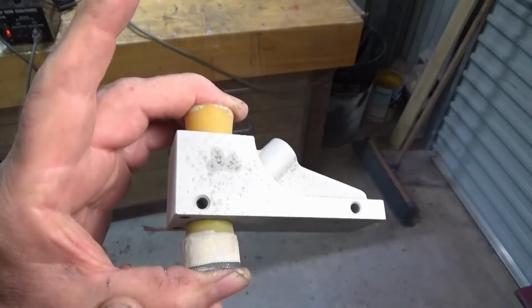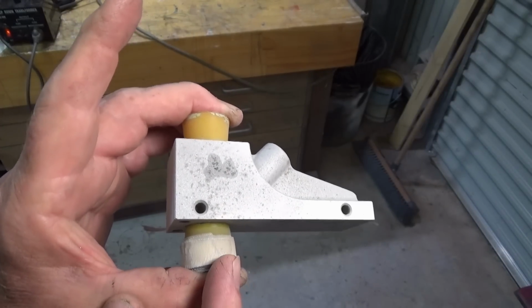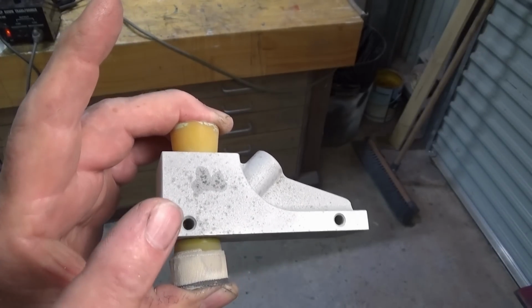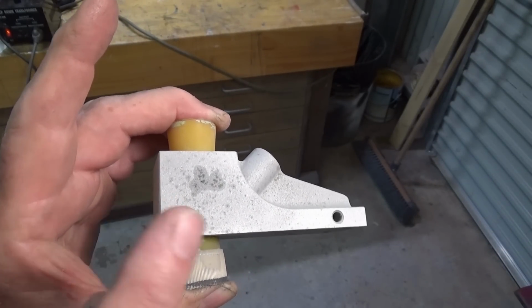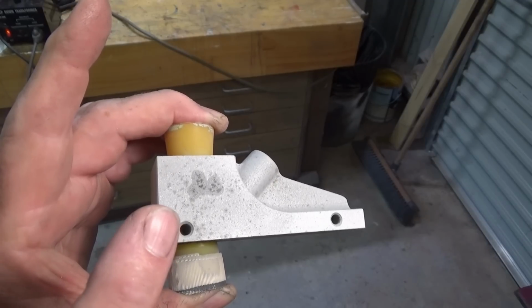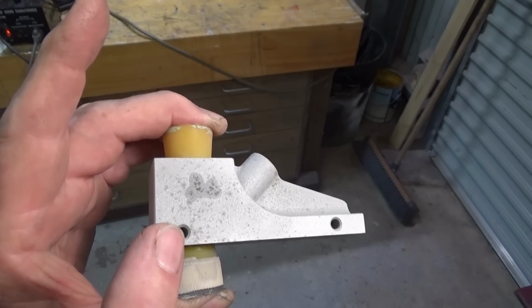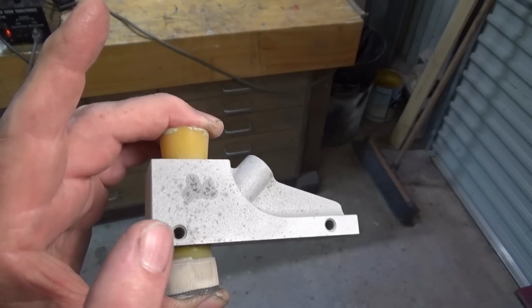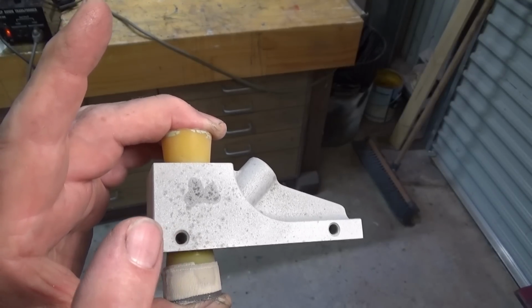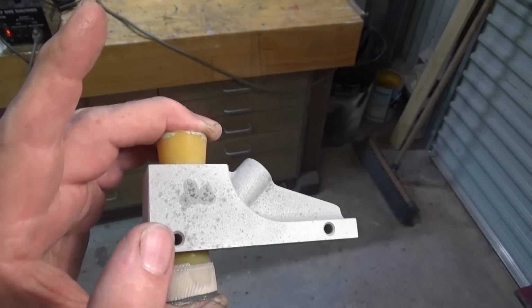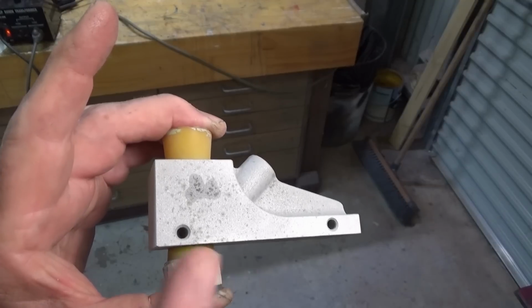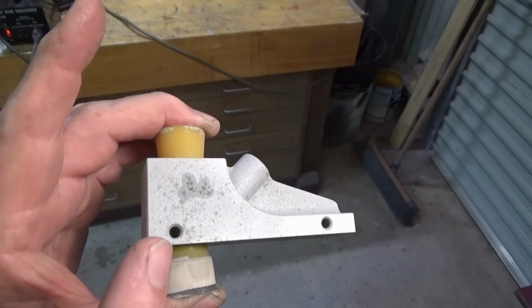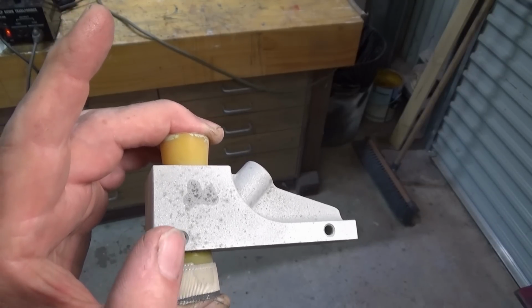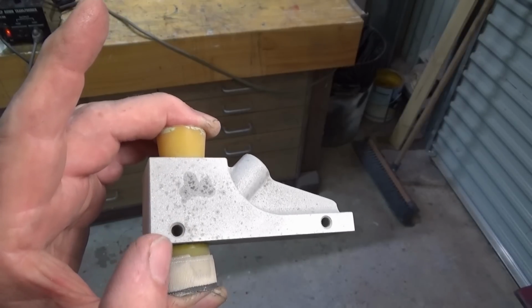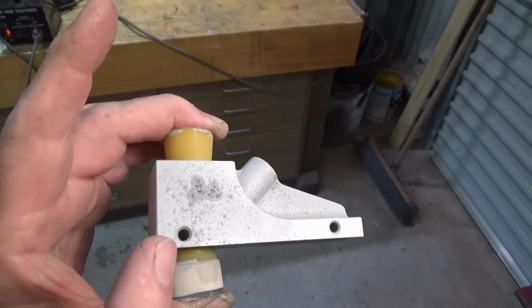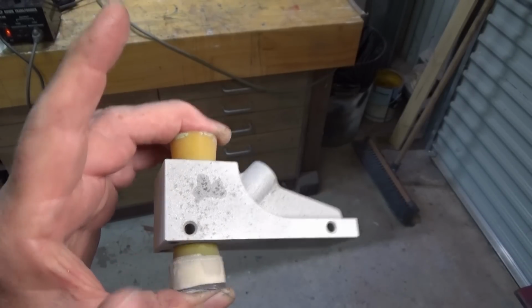I just left this casting on the bench for a while after I've sandblasted it, and you can see a problem there. So there's some porosity in this casting, and during the machining process it's absorbed some oil, and now it's starting to bleed out onto the surface. Now if you don't do anything about that, the powder coat won't really adhere in that area, and it'll leave pinholes and bubbles in the surface. So I'm going to put this in a really hot oven and try to dry off or burn out that oil. And then we'll also do it in the ultrasonic cleaner.